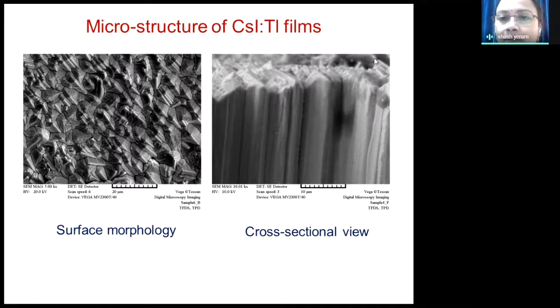So whenever a high energy photon, a gamma photon or X-ray, like we are doing X-ray, comes and impinges here, it is absorbed. Whatever burst of photons it gives up gets collimated. It stays within this one needle, then travels and gets detected with the photodetector. If we keep a spatially resolved photodetector on top of this film, whatever information comes from the photon impinging on this part is coming from this. So there is a lateral one-to-one correspondence because of this needle-like structure; the photon burst which has been produced will not go in any other direction, it will be collimated in this. This leads to very good spatial resolution, otherwise there would be crosstalk. So this is one way.